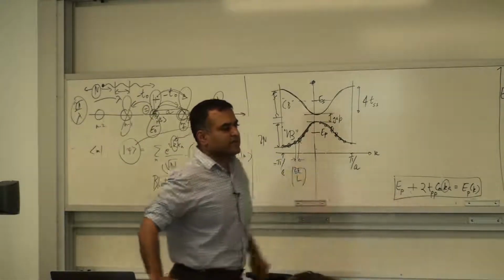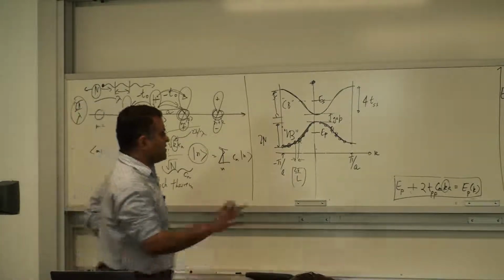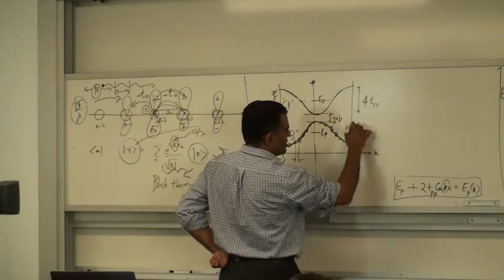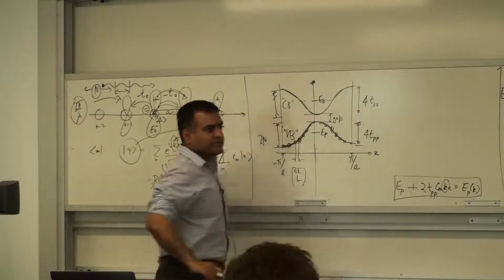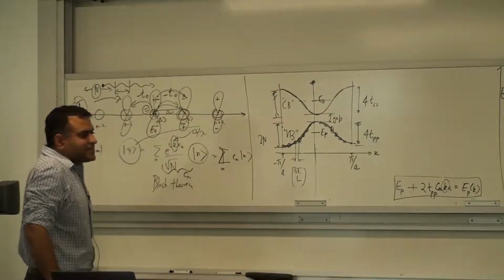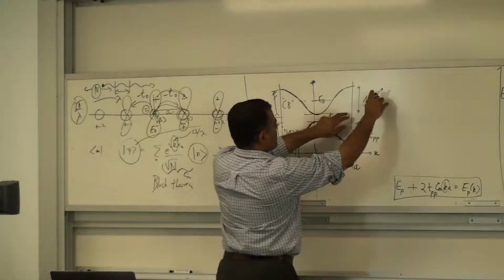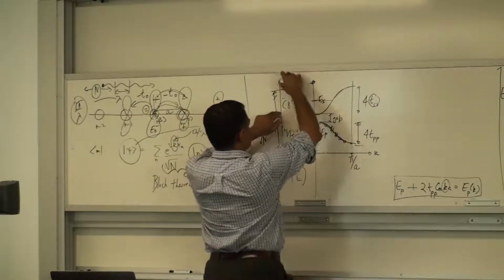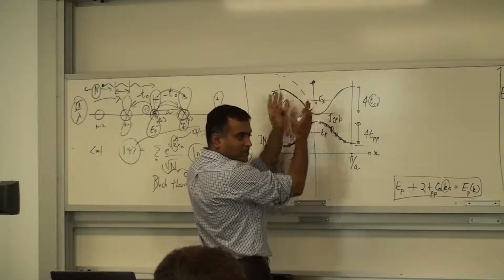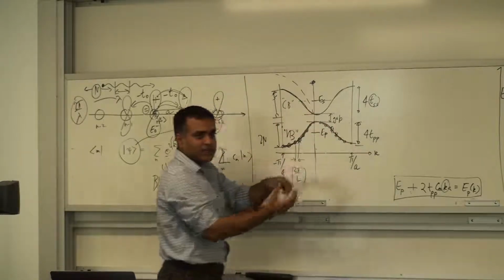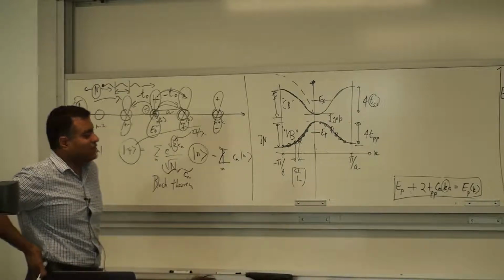And the bandwidth is proportional to this T0. Absolutely, yeah. So that's a very important point. Bandwidth is proportional to the ease of hopping. Easier to hop means a larger bandwidth, so more steeper. Exactly. So all these are connected. That's right. So if this is large, then this stretches out, and your curvature here goes down. So the effective mass is small. The electron is effectively lighter, and so it can move faster and has higher mobility and all that sort of thing. Absolutely, this is all connected.